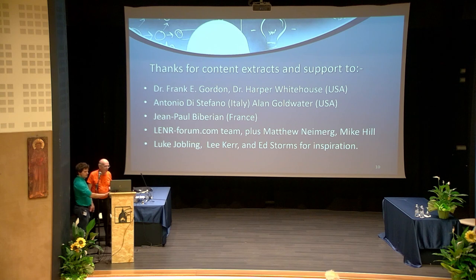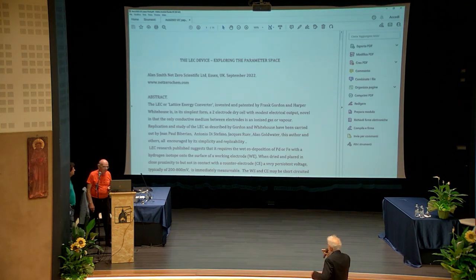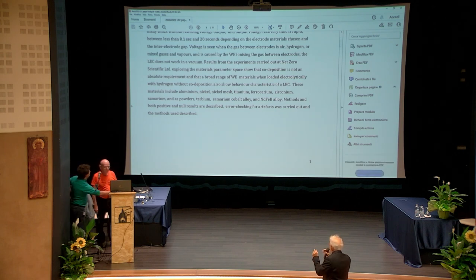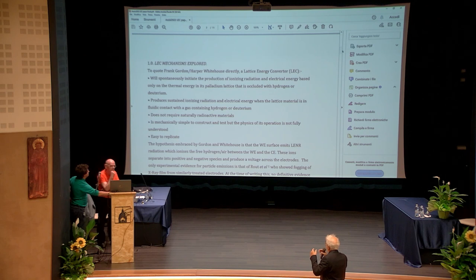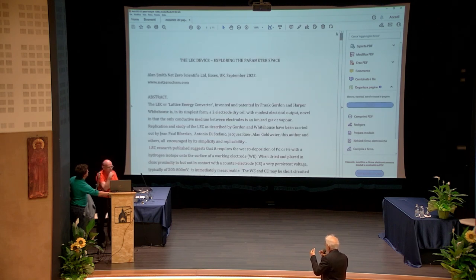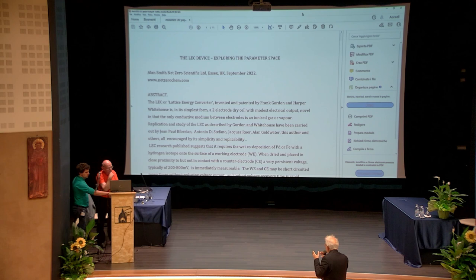Sorry, did you have a question? Thank you very much. I informed at the conference in the United States, ICCF24, we sometimes observed such kind of phenomena, but in our specific environment, distance about 2 millimeters, the effective surface area of the active electrode is about 1 square meter. The counter electrode is iron, and this effect doesn't happen at the beginning, only after 1 week of absorption of hydrogen. And the voltage typically, but it's not regular, from about 100 millivolts up to 500, 600 millivolts. The typical current is the weak point, only a few microamperes. This was a bursty phenomenon.